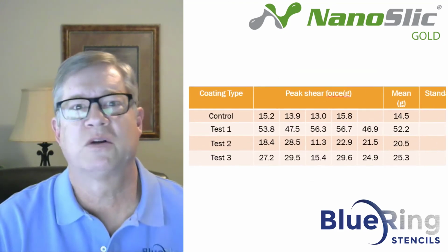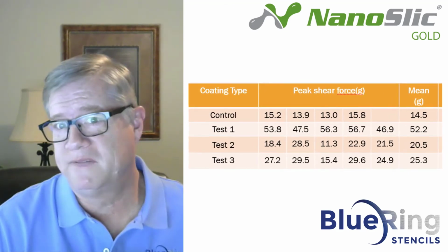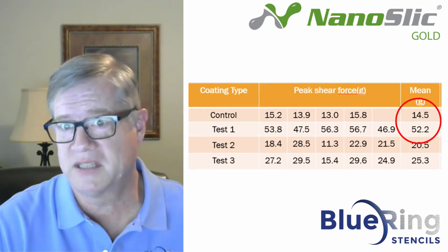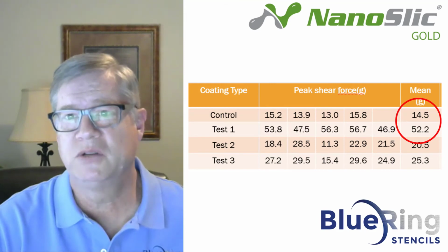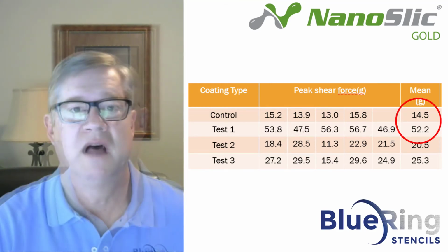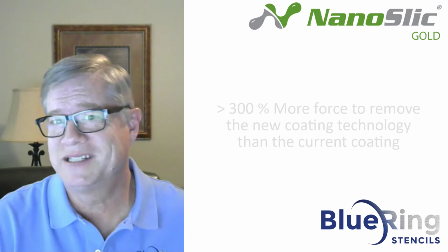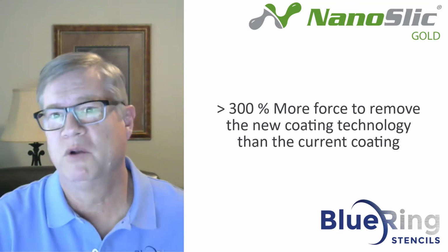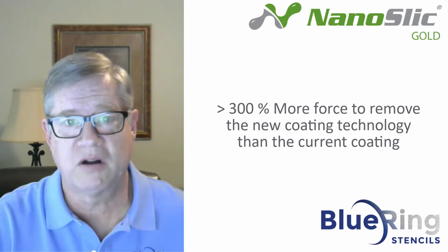able to increase the force required for removal from a mean of 14.5 grams for our current process to 52.2 grams for this new process. In other words, it takes over 360% more force to remove our new coating technology than our current coating.